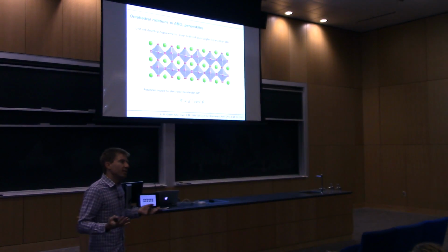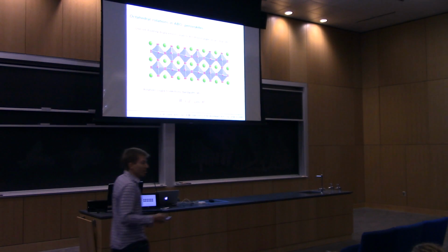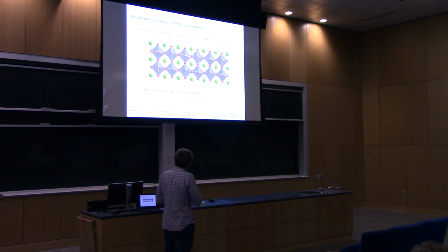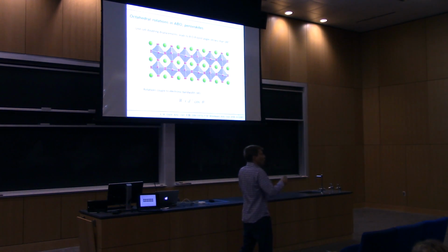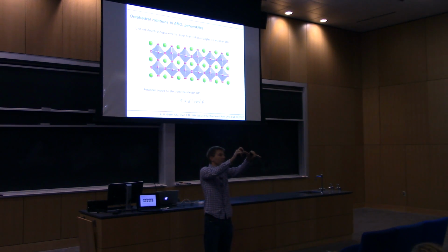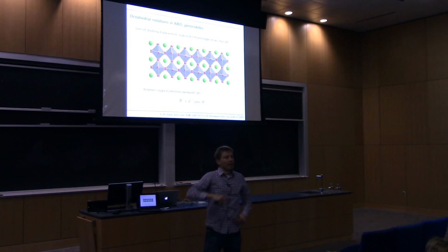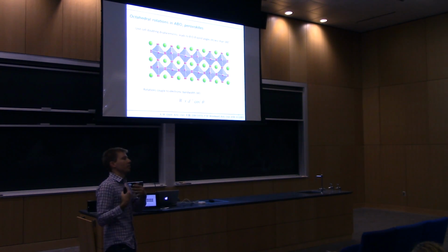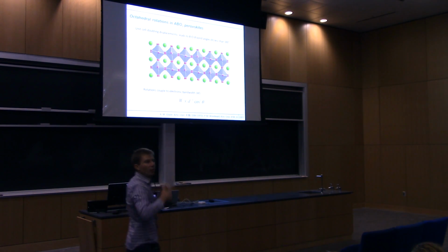So we can have bond angles that are like 160 or 150 degrees, right? And this is not just a neat crystallographic feature. These bond angles directly couple to the electronic bandwidth. So in general, this theta is the B-O-B bond angle, and this d is the B-O bond length. Okay, so as I crank up the magnitude of these octahedral rotations, as I reduce theta, my electronic bandwidth will go down.